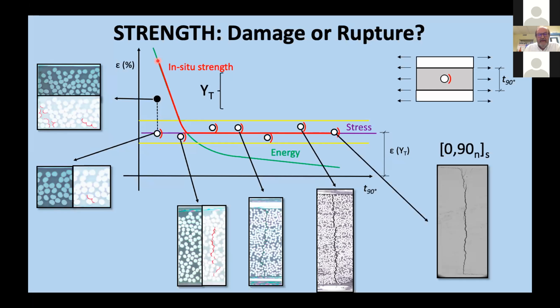So, to conclude, how are we going to proceed? If we want YT to be associated with the appearance of damage, then this value is correct for all types of thickness. If, on the contrary, we prefer, which is the typical approach, to have it associated to the rupture in general terms, probably it would be better to refer to this situation as failure stress. And it would be even better to give a designer some indications about values that he can reach, not putting into question the integrity of the laminate.